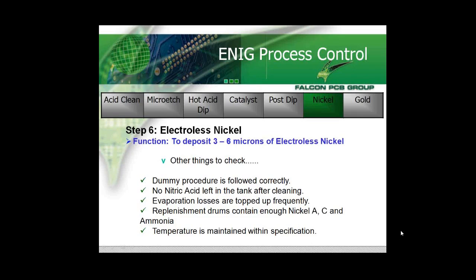Again, important that evaporation losses are topped up very frequently, and of course what we have to do is to make sure that all the replacement drums which feed the dosing pumps, again, do not run out. Any imbalance at all in this process will turn around and the bath in one form or another will fail to work.